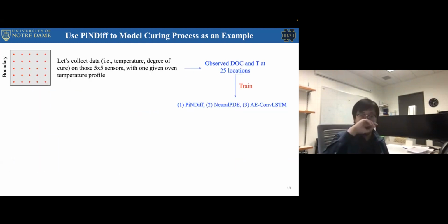So then we started to do some experiments. Let's collect the data. This is the composite, our sample, and we're going to collect data like the temperature and degree of cure on these 5x5 sensors, with one given oven temperature profile. Then we will observe the degree of cure and temperature at these 25 locations, and then we train those 3 models. PINDIF is our model, and the other 2 are black box baselines.